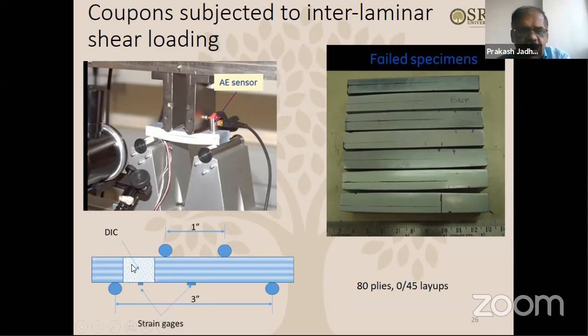And we also painted this region. We polished the surface of the specimen and painted this region with special powder, because we wanted to monitor it using digital image correlation. So what is this digital image correlation technique? I will explain that. A digital image correlation technique is basically you have this very fine powder coated on the surface of the specimen, or very fine paint that's coated on the surface of the specimen.